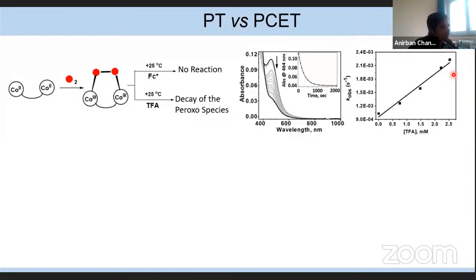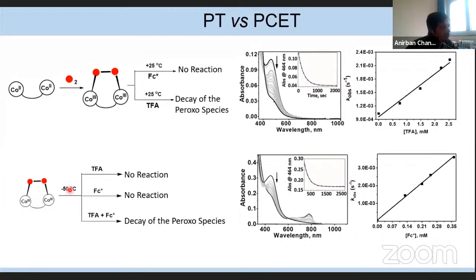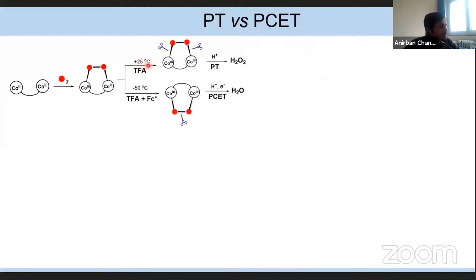And this decay follows a nice first order kinetics, and from this value I am able to determine the second order rate constant. Whereas when I check this same reaction at low temperature, I found that this peroxo species is stable in presence of acid if there is no electron source, and in presence of only electron if there is no acid. So as you can see, if I add acid, there is no reaction. If I add only electron, there is no reaction. But if I add both the proton and electron together, then the decay of the peroxo species takes place. So that is suggesting that at 25 degrees centigrade, it goes via a proton transfer process where the metal-oxygen bond cleavage takes place to produce hydrogen peroxide. Whereas at low temperature, in presence of both proton and electron, proton coupled electron transfer takes place where O-O bond cleavage occurs to form the water.